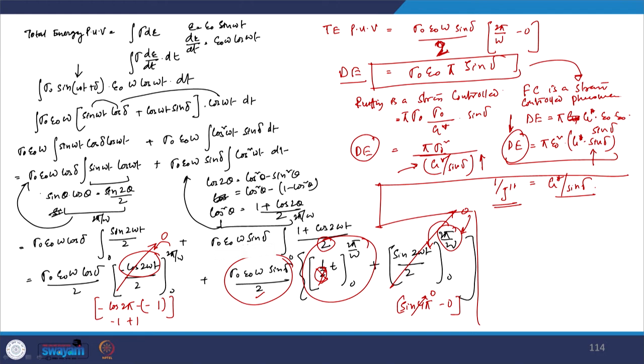One thing which maybe I missed in my previous presentations was that when we are talking about viscoelasticity, you cannot just compare the compliance with the relaxation modulus, which means you cannot write directly that, let us say, G star is equal to 1 by J star. Well, this is wrong, and therefore we have to understand that since this is a viscoelastic material and there are a lot of delayed elastic, retarded responses, they cannot be equated with each other because they are altogether different forms of testing modes. I will try to give you an insight into how J double prime becomes equal to G star by sine delta, and it's simple because this is something which we have already discussed.